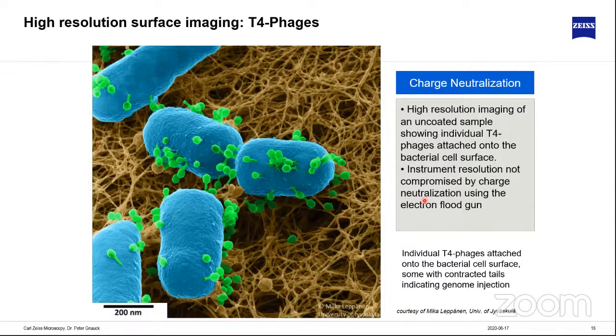We can also very nicely image biological samples. And the reason is we're very surface sensitive. We have a high resolution and we're not sensitive to charging. And what we can see here, these are bacteria which are attacked by phages. And what you can nicely see is how these phages attach to these bacteria.